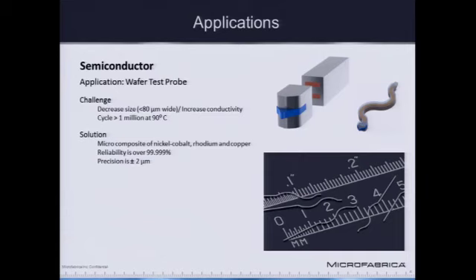So what are some of the challenges of this? The industry, with Moore's law, all the chips are getting smaller and smaller. So are the pads on those chips. So the pitch on those pads are getting smaller and smaller, and they need to touch down on all those pads to make electrical contact. So these needles are getting, in the same way, very, very small. Less than 80 microns in diameter going to probably less than 50 microns in diameter. And at that point, precision is really, really key. Every micron counts.